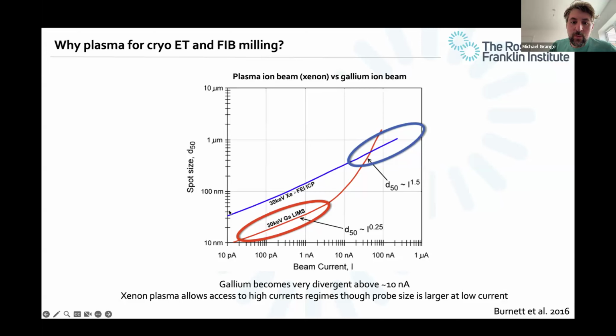So the idea was, can we use plasma to essentially have very high extractions, very high milling rates, but also try and preserve some of that ability to mill very thin material? So you can see on this plot here, the probe size for plasma ion beams, in this case xenon, is much larger than gallium by a factor of around 5. So can we actually use these ion beams?